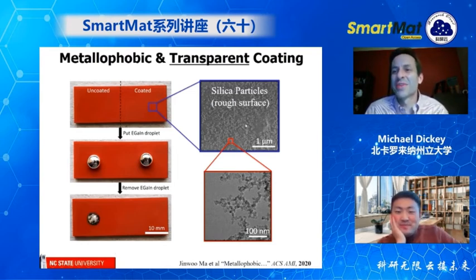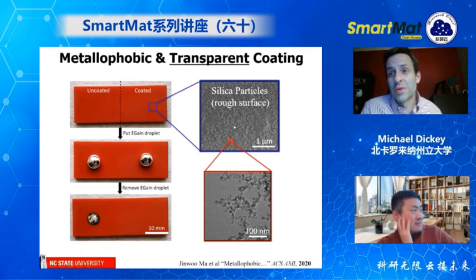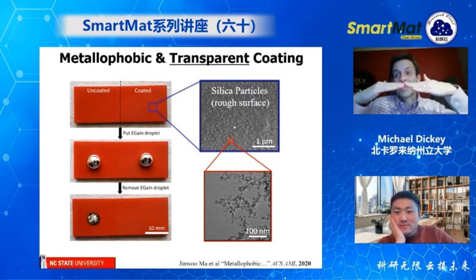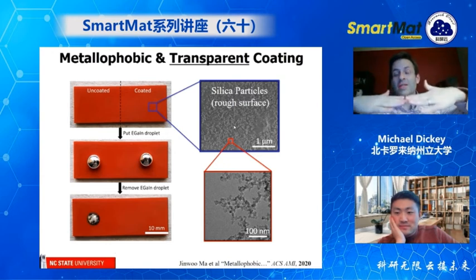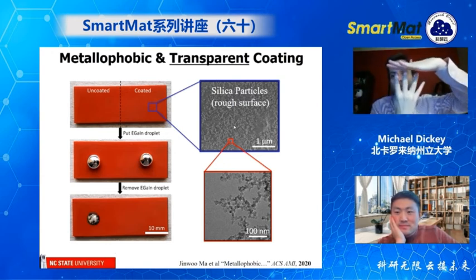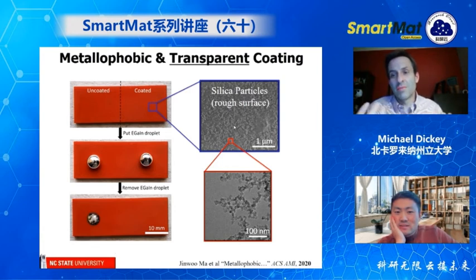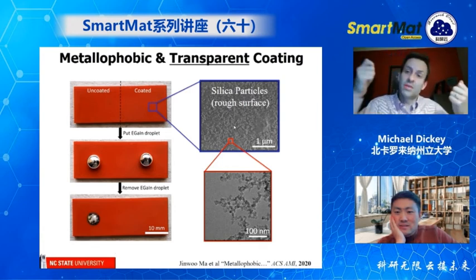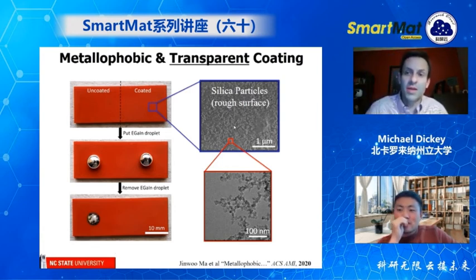This is what the surface looks like. It's rough, very much like a Cassie-Baxter state. And so what happens, I think, is that the oxide layer cannot make good contact to the surface. So it's like sitting on a bunch of little posts, and it doesn't have very many contact points. And so it's easier to peel the oxide off of the surface.